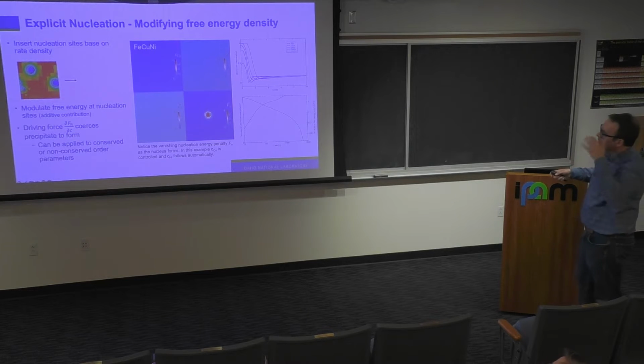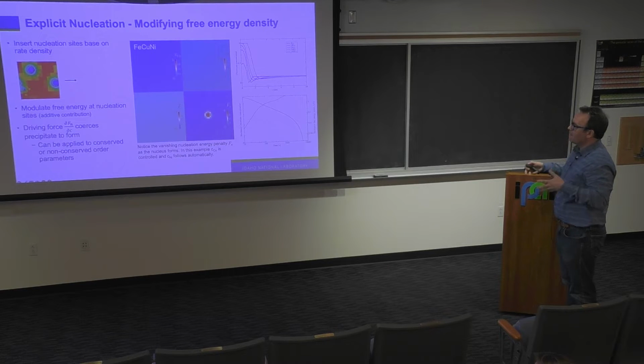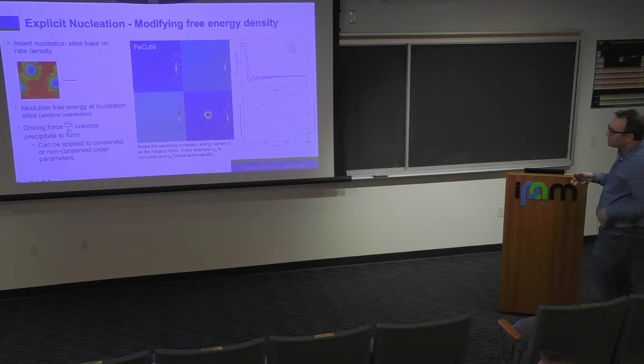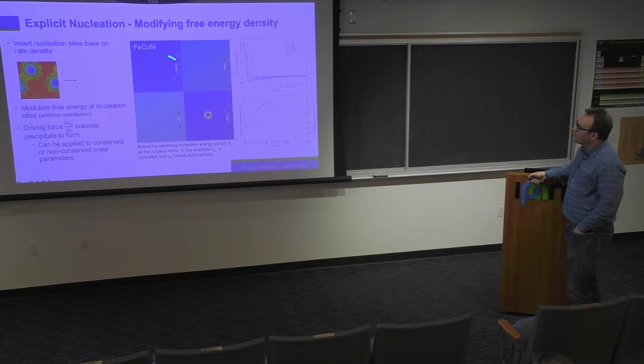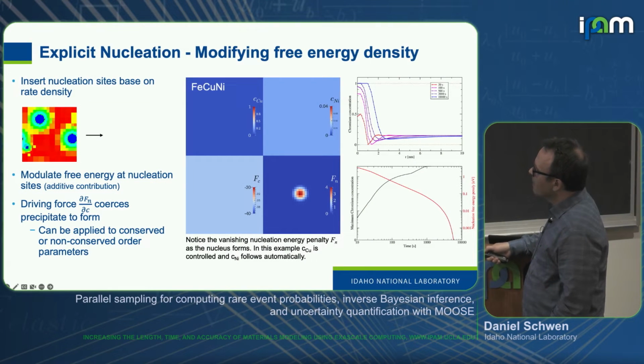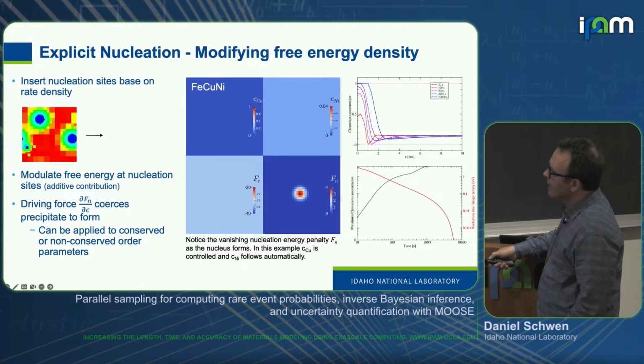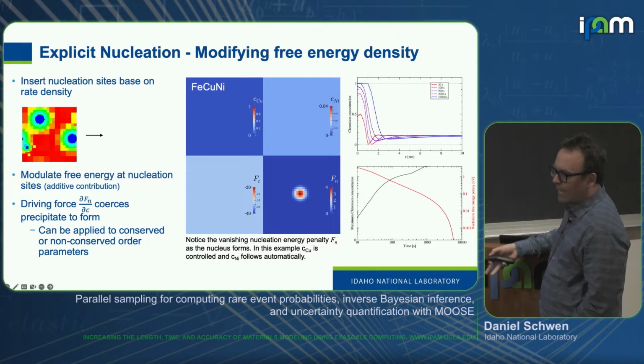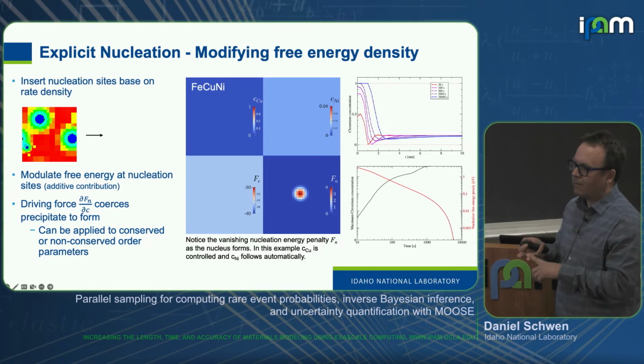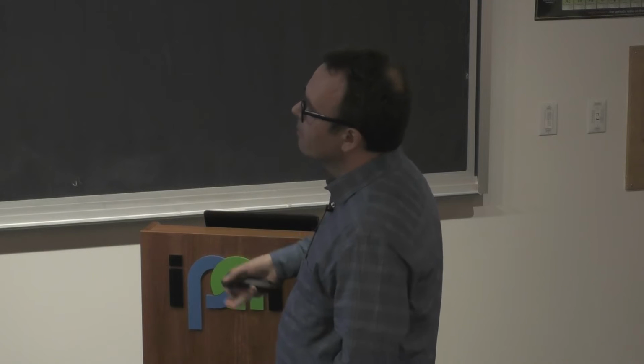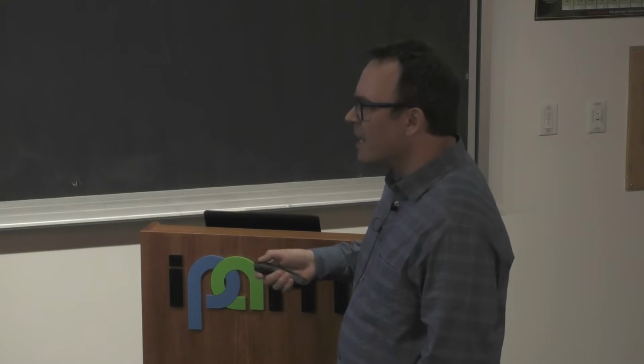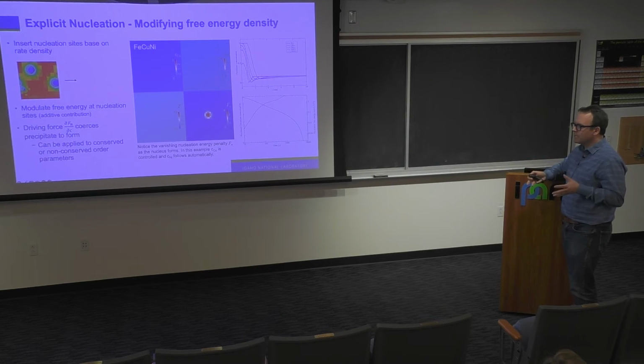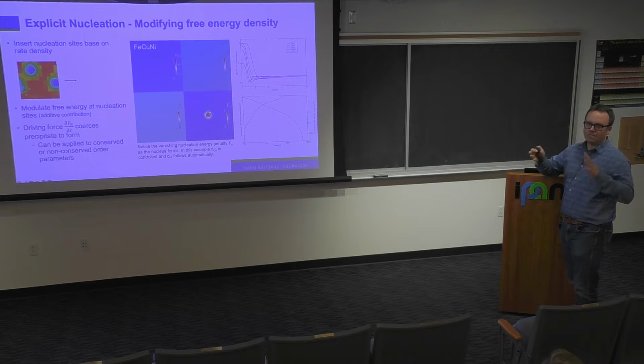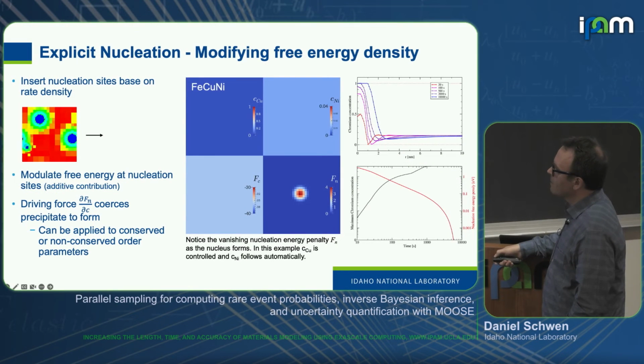Rightly, people have remarked that phase field does not intrinsically have the capability to capture fluctuations and model nucleation events, but those are actually pretty important. And what I've developed for that is this explicit nucleation scheme, where we modify the free energy density to cause nuclei to appear, and that works by calculating a probability map for a nucleation event to happen, which can be based on classical nucleation theory or heterogeneous nucleation probabilities. Unfortunately, it doesn't come from the phase field, but you have to put it on top of it. And actually, this is not a big drawback, because for the real engineering type applications that we want to model, we could not get the right nucleation rates from phase field anyway, because our samples are dirty. Nuclear fuel is never single crystalline, has defects, has impurities from burnup, et cetera. So we're better off fitting to some experimental data here.